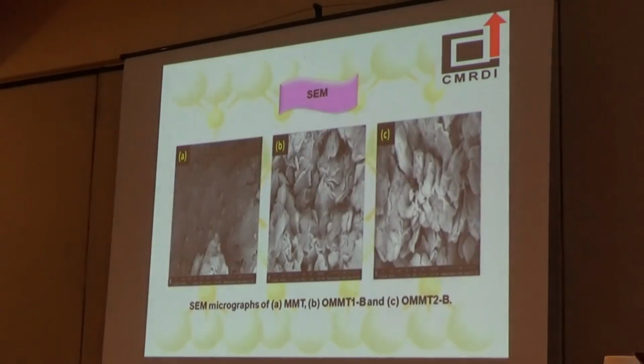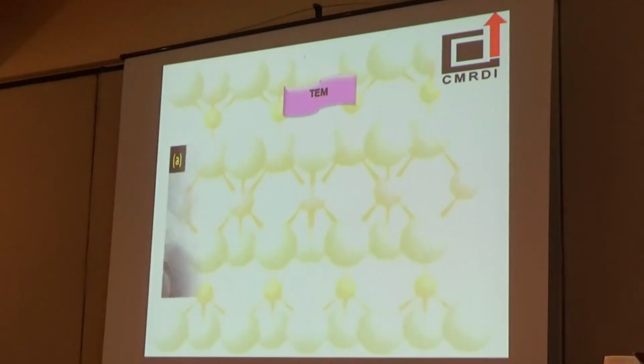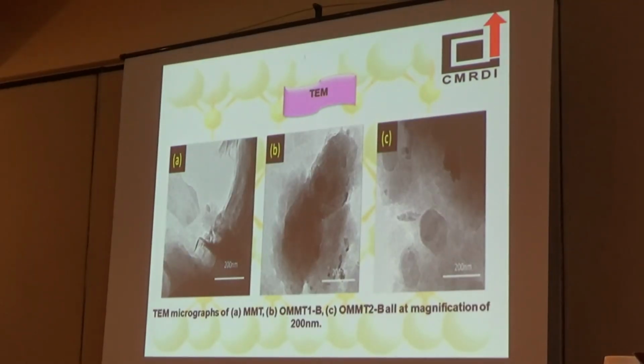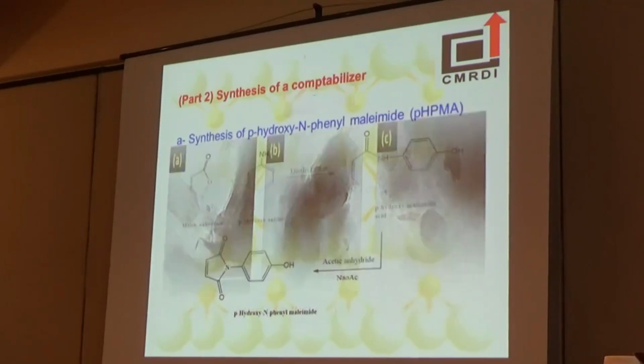The scanning electron microscope of the modified clay sample shows a massive thin layer structure with some interlayer spaces, which confirms the modification process. Also, transmission electron microscope shows that there are particles of dimension 100 nanometers, and this result supports the XRD and scanning electron microscope results.